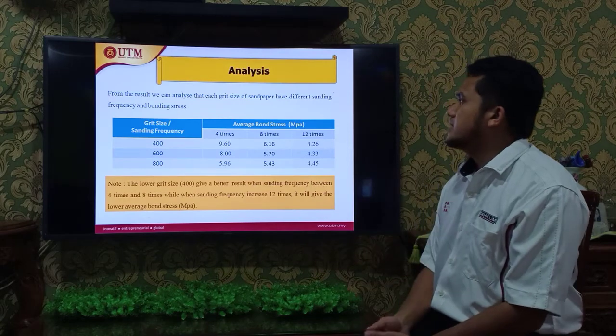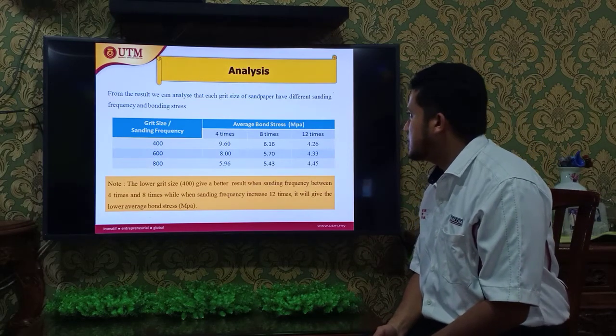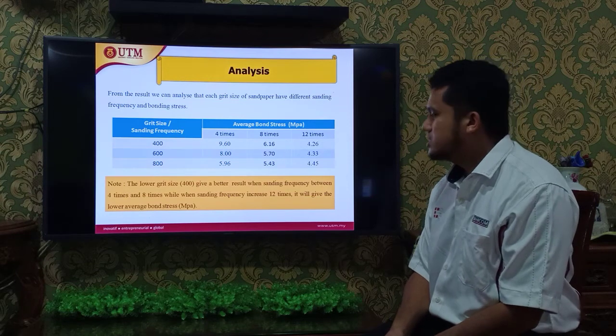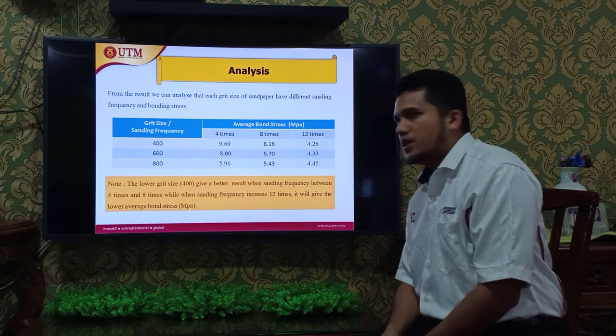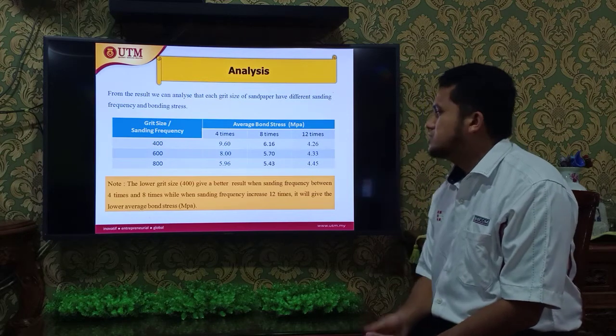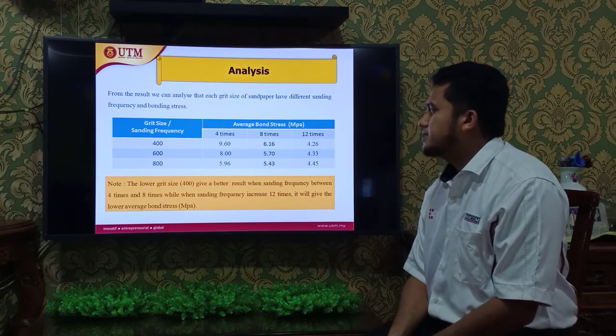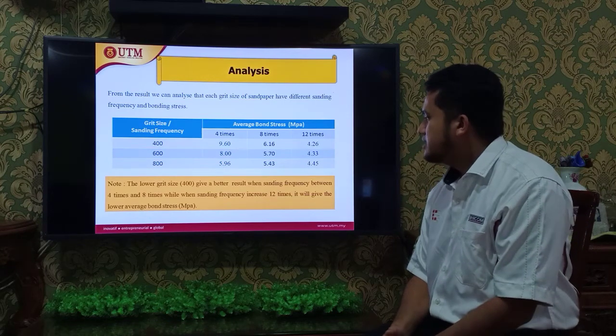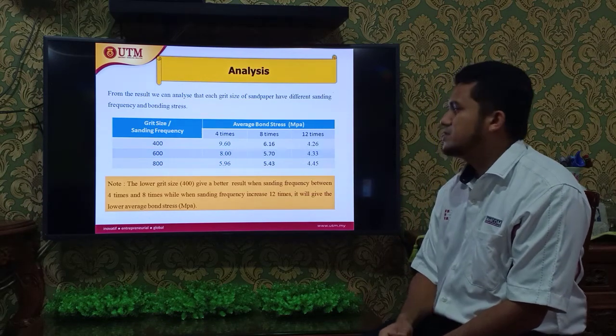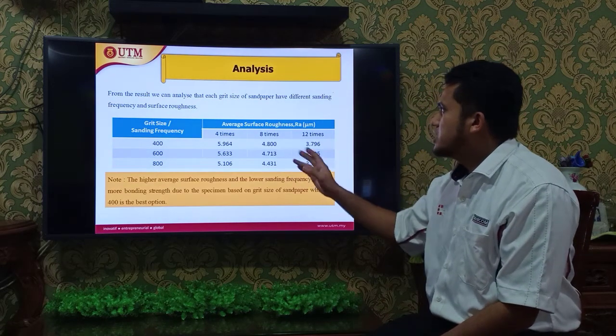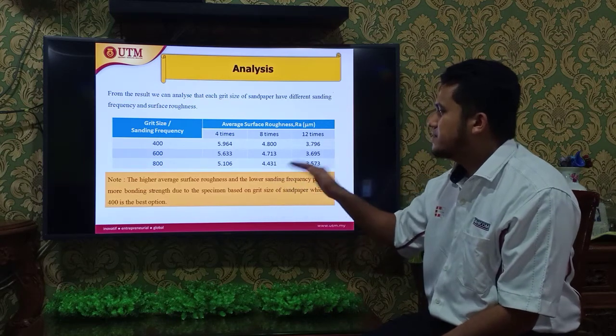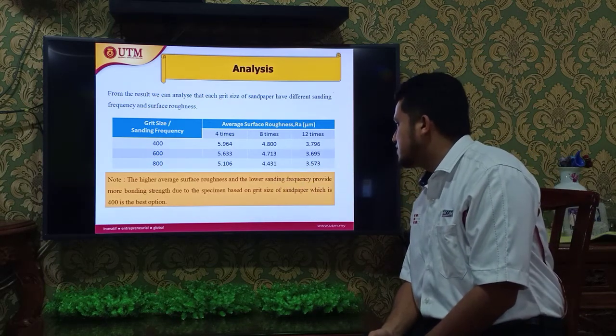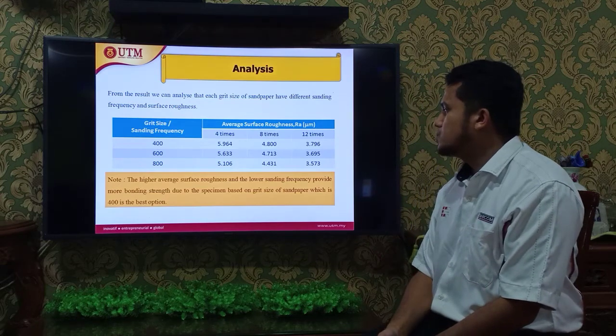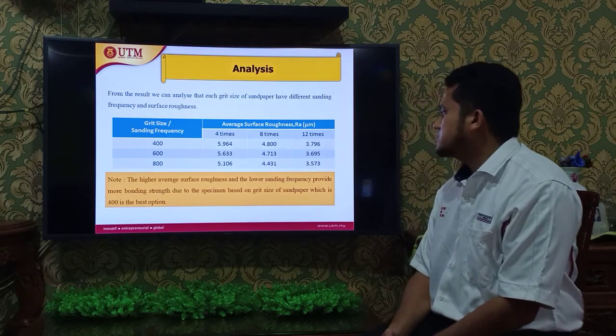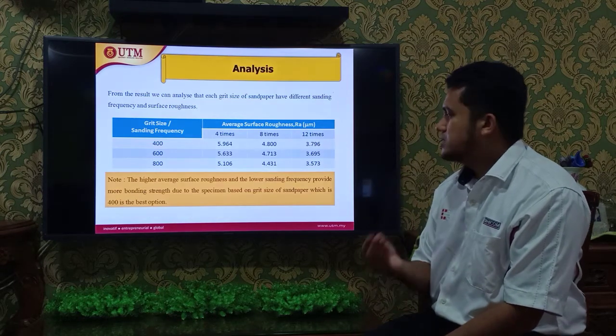From the result, we can analyze that each grit size of sandpaper has a different sanding frequency and bond stress. The lower grit size 400 gives a better result when the sanding frequency is between 4 times and 8 times, while when sanding is increased to 12 times, it gives a lower average bond stress. For the surface roughness, the higher average surface roughness and the lower sanding frequency provide more bonding strength, and based on the grit size of sandpaper, 400 is the best option.